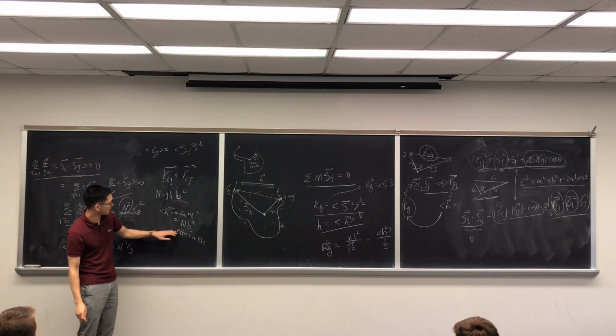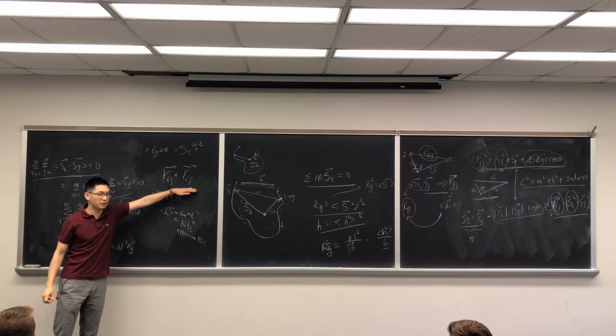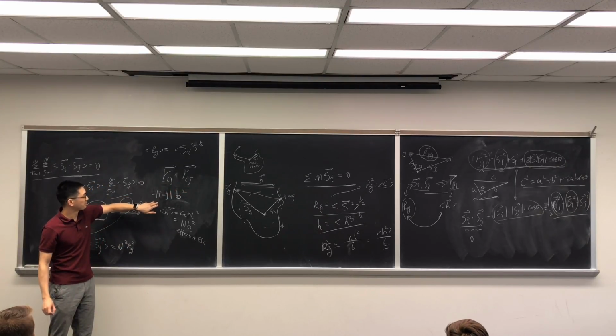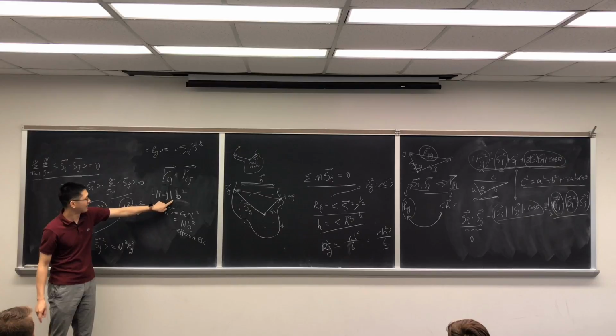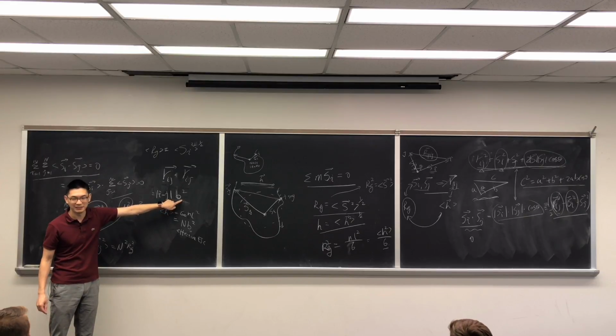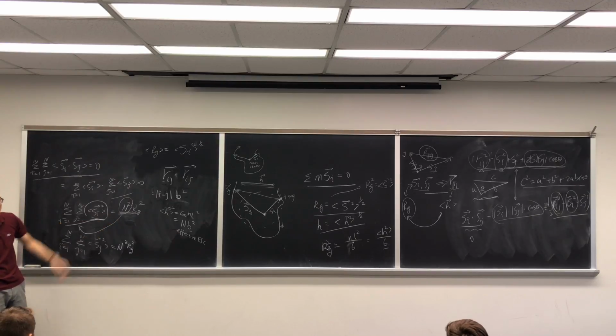So these are the basics. In other words, what we are doing is converting any distance between two bonds to this |i minus j| b squared or C infinity |i minus j| L squared. And it will be very useful, you will see.